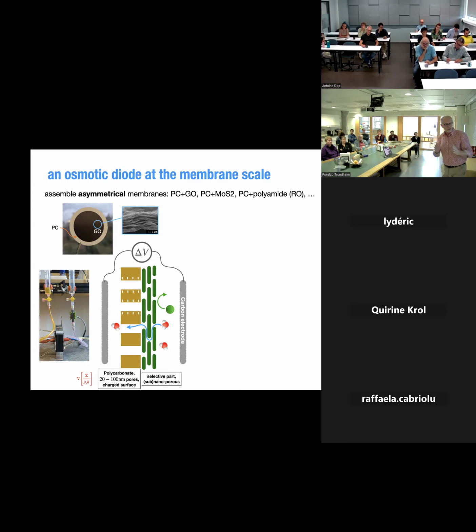And so what we did as a system, that's typically an experimental setup, it's just a cell where you take this and sandwich it between two electrodes. Usually we use carbon electrodes because they are extremely standard. And you just press it, put a voltage in between, and start measuring.